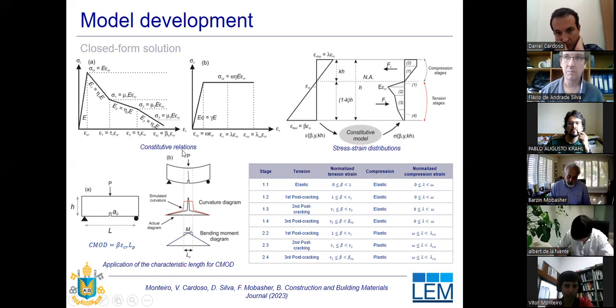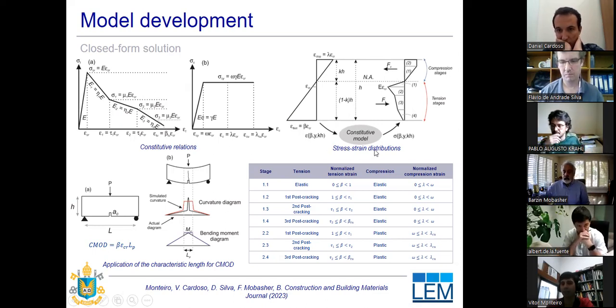After the constitutive relations are carefully analyzed, we can go to the stress strain distributions and calculate the stresses along the crack section of the FRC. So we assume linear strains, Kirchhoff hypothesis, and assuming that the flexural rupture of the beam is controlling the main mechanical behavior of the FRC at the material level. However, there is still a major parameter that we need to carefully analyze in this model, which is the CMOD. This is very important because, as we saw in the beginning of the presentation, the CMOD is monitored by the clip gauge along the fatigue test. So it is a key parameter.